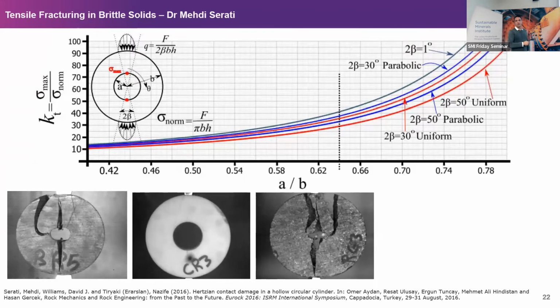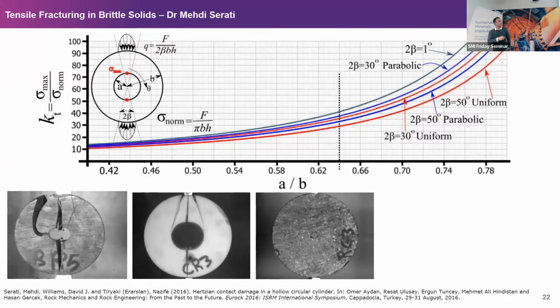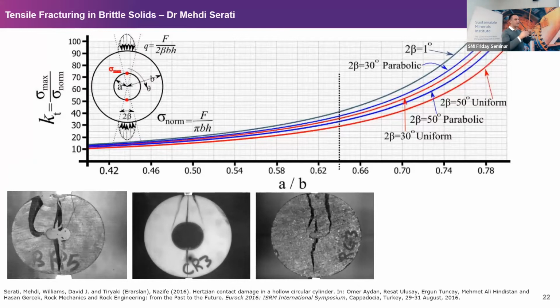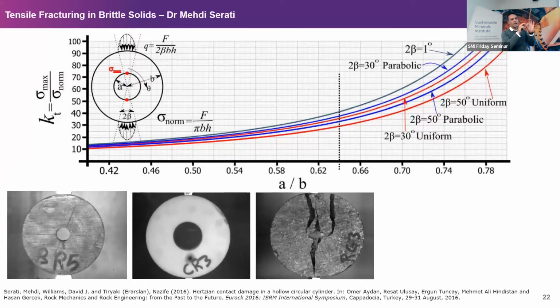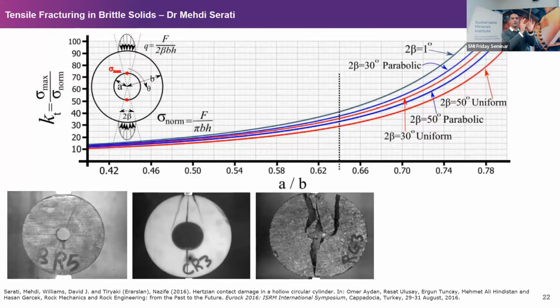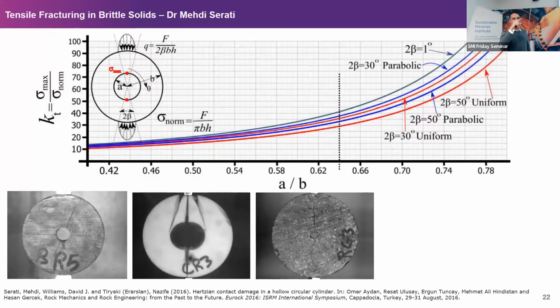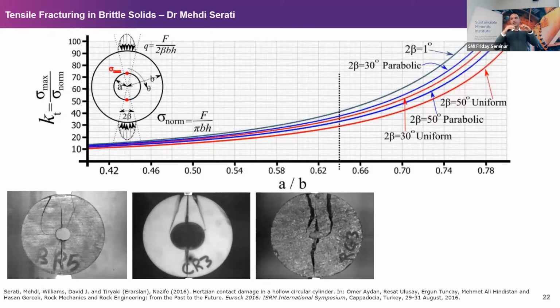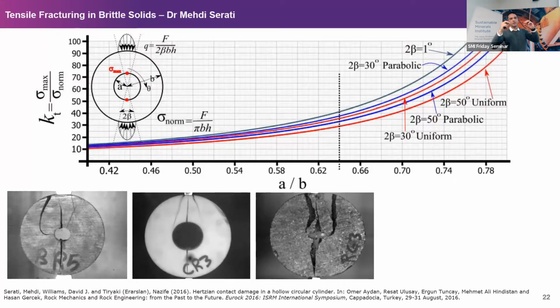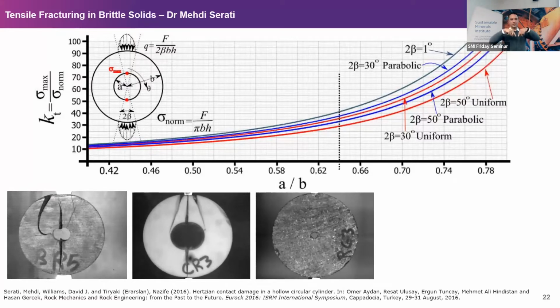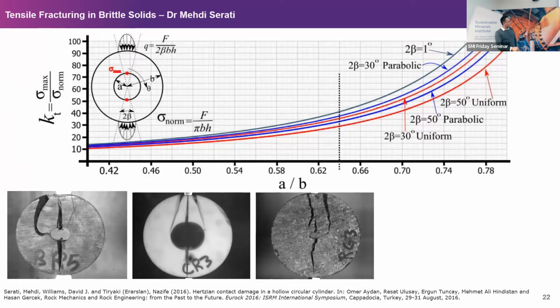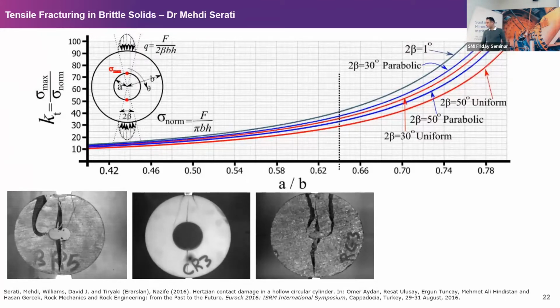We didn't know what was contributing, but using this theoretical framework, we could prove mathematically that if the ratio of the hole to the diameter of the sample is beyond a critical point, there are always 4 points inside the disc that reach the tensile strength of the material. Therefore, you get 4 tensile cracks and not 2. If you're interested, we have explained it in a now almost 6-year-old conference paper.